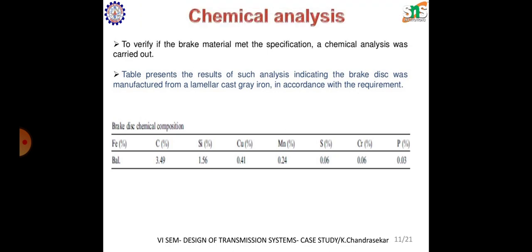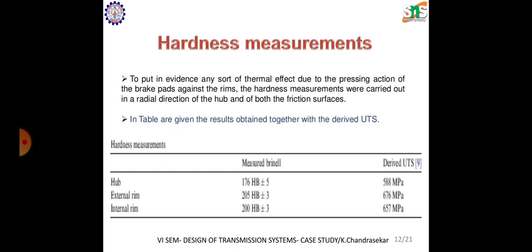Then chemical analysis was also done to verify whether the brake material met the specification. A chemical analysis was carried out. The table below presents the results of that analysis, indicating the brake disc was manufactured from a lamellar cast grey iron in accordance with the requirement. Okay. Then hardness measurement was also done. To put in evidence any sort of thermal effect due to the pressing action of the brake pads against the rims, the hardness measurements were carried out in a radial direction of the hub and of both the friction surfaces. The results obtained together with the derived UTS are shown here.